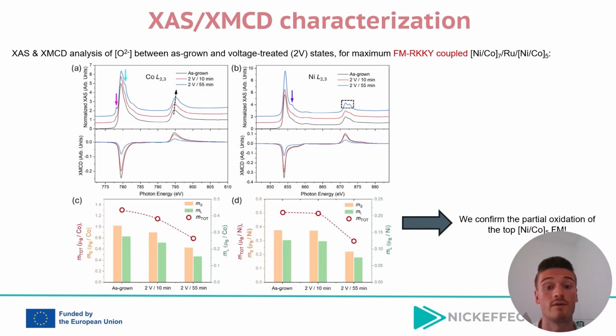To further understand the atomic scale origin of the magneto-ionic phenomena, X-ray absorption spectroscopy and X-ray magnetic circular dichroism characterization was carried out in the studied heterostructure in both as-grown and voltage-treated conditions. If we closely look at panels A and B, we can see the XAS and XMCD spectra for both cobalt and nickel, highlighting the spectral changes, particularly the emergence of features that indicate partial oxidation upon voltage treatment, such as this shoulder appearing at the XAS spectrum.